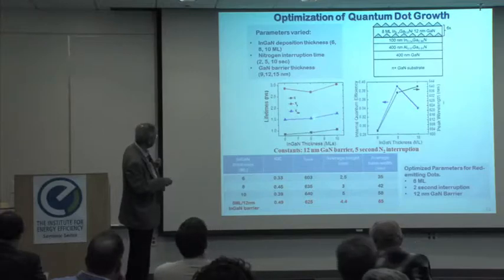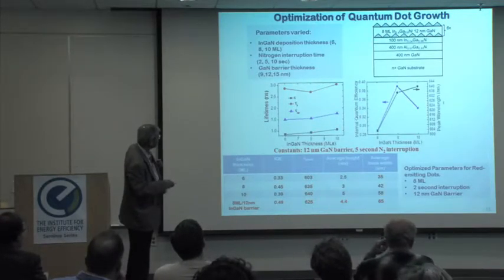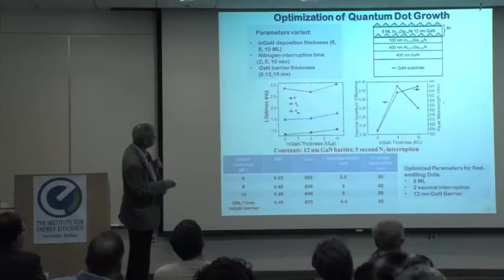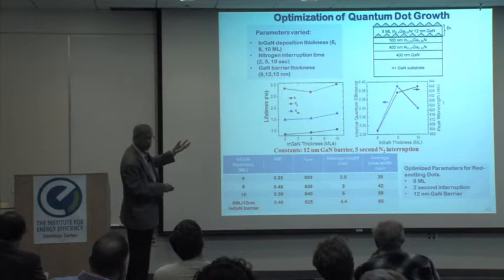And you see the radiative, non-radiative, and the total lifetimes. And here you can see the internal quantum efficiency and the peak wavelength. As the dot gets larger, you can see that the emission wavelength also moves to longer wavelengths. And you can see here you have the optimum electron hole overlap, but if the dot becomes too large, then of course the overlap decreases.